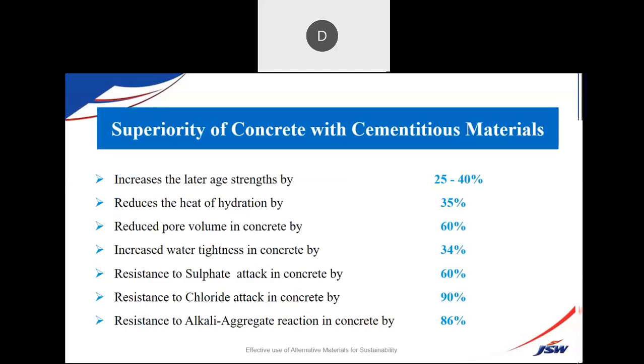Looking at the overall performance, various research articles have compiled these parameters on how mineral additives like GGBS are improving the performance of the concrete. Later age strength, 56 days, 90 days strength, is going to show a 40% improvement. I've seen it through my own eyes. In my own buildings, I implemented casting cubes for 56 days, 90 days. I did this when I constructed my house. I could see a substantial gain. M25 grade concrete had become M50 grade concrete, which I tested at almost 90 days. That was the advantage of using mineral additives. Reduction in heat of hydration, so thermal cracks are avoided, and reduced pore volume by 60%, increased water tightness by 34%, and sulfate attack, chloride attack, and alkali silica reaction. You can see a substantial reduction compared to the control mix when you use these alternative materials, called mineral additives.